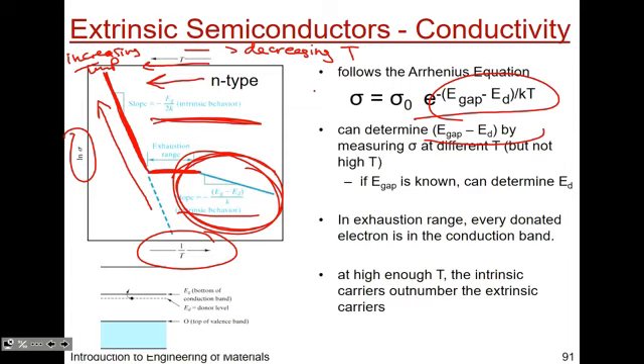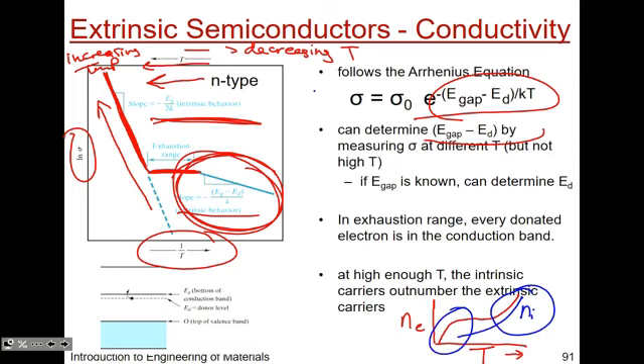So if you plot temperature, where temperature is increasing this way, and let's say you're looking at the number of charge carriers for electrons or holes, it looks something like this for extrinsic, and for intrinsic, it looks like this. So all this means is that at higher temperature, the intrinsic carrier concentration dominates the behavior of the conductivity of your material. At lower temperatures, it's the dopant concentration that matters. Okay. So that's for N-type.